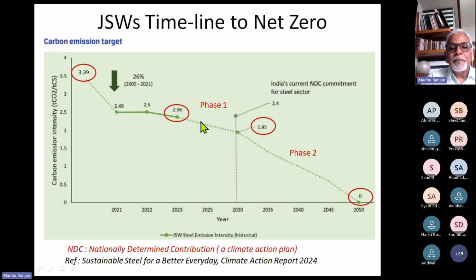So here is the timeline prepared by JSW for reaching net zero by 2050. What has happened is that from 2005 up to 2023, they have reduced their emission rate from 3.39 to 2.38, and we can say this is the current rate. Going forward, they have split the entire strategy into phase 1 and phase 2. By 2030, they have planned to reduce the emission intensity to 1.95 by various actions, which we will see. And by 2050, they have various actions charted out, which will make it net zero.